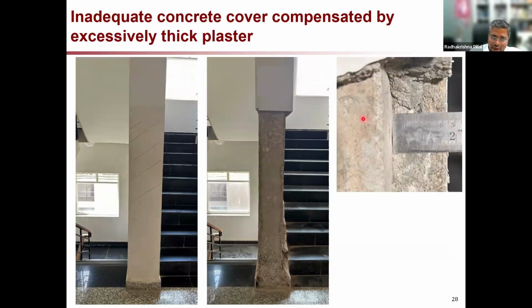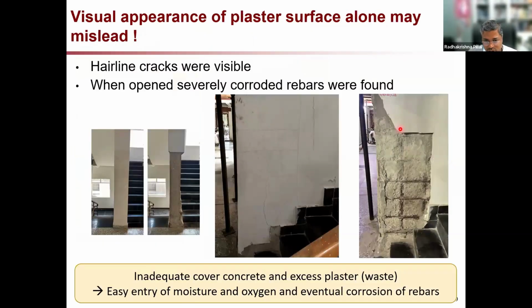That means on the other side of the same column, it will be much less. So there is a significant variation in the cover. Cover depth is not adequately provided in many, many cases, which leads to significant, early corrosion issues. When we opened it up, you could see a lot of cracking, this hairline crack, very, very fine cracks. But when you opened up, you could see the significant corrosion here.